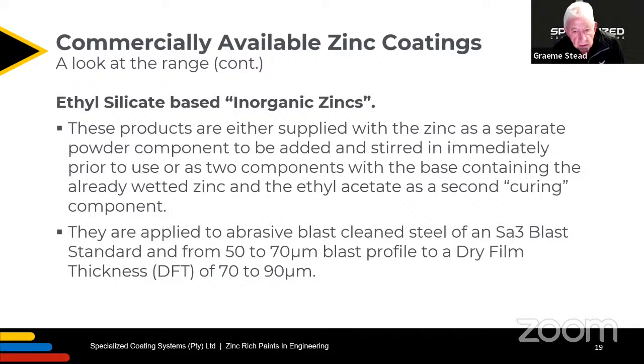Now the preparation of steel to SA3 is a controversial subject, and that is in fact why a standard of SA2.5 was adopted, because the contractors argued that it was not practical and very expensive to achieve an SA3, which is a clean blast. So SA2.5 is slightly lower than that, but I emphasize that the quality of the preparation is of utmost importance, and the dedusting and quick overcoating of the blasted surface is of paramount importance.